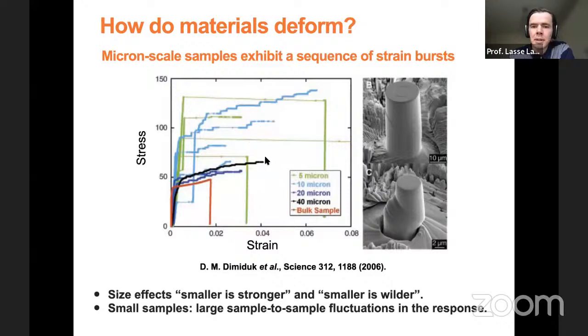And this is a stochastic thing. So it looks like these are, roughly speaking, random. Also, if you repeat the experiment using a similar sample, the same size, same preparation protocol, you will get sample-to-sample fluctuation. So even if you've got similar samples, the response will be a bit different every time if you're looking at small samples like this. There's also another size effect here, which is that larger systems at a given strain tend to have a larger stress.